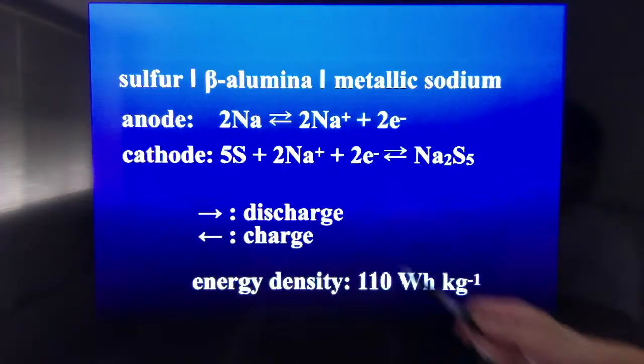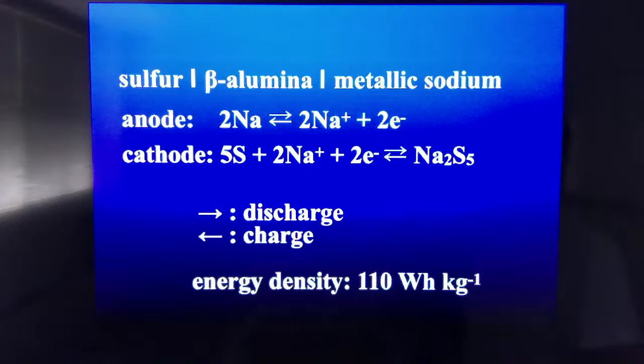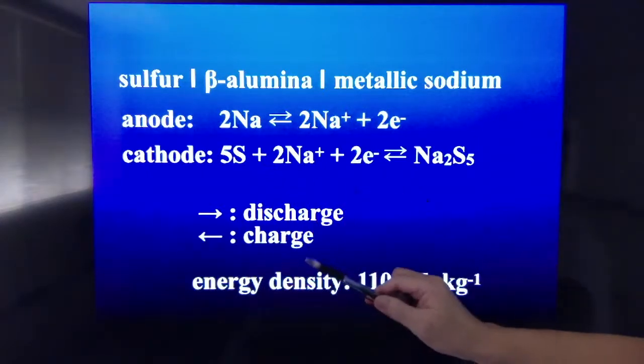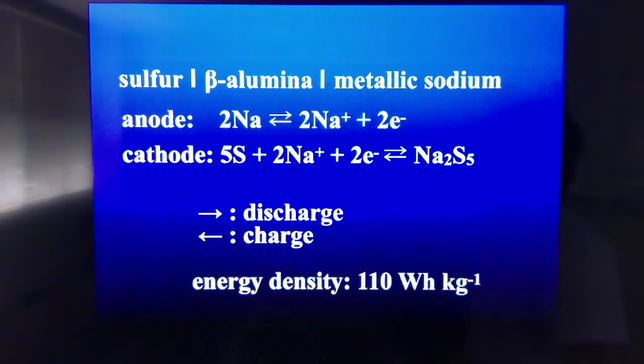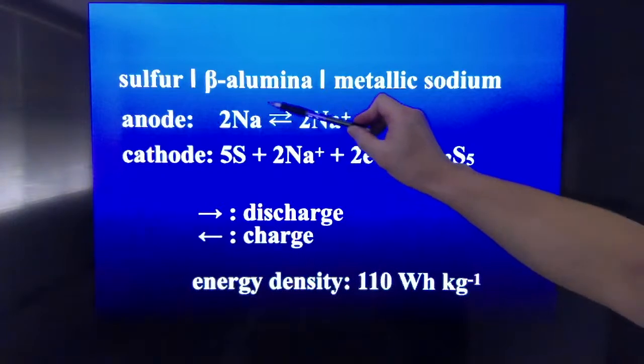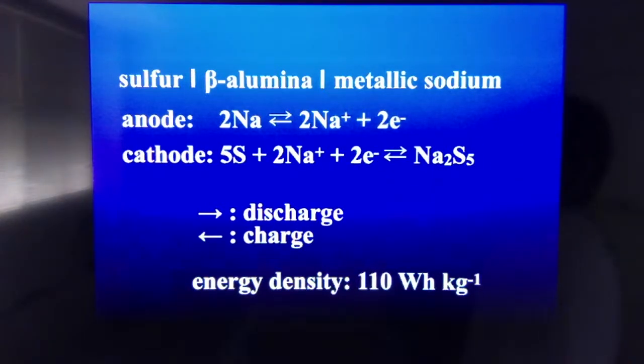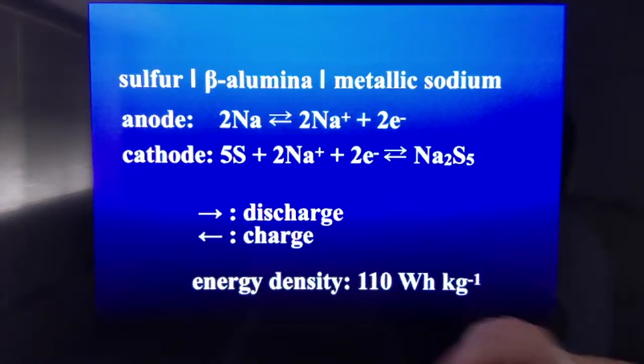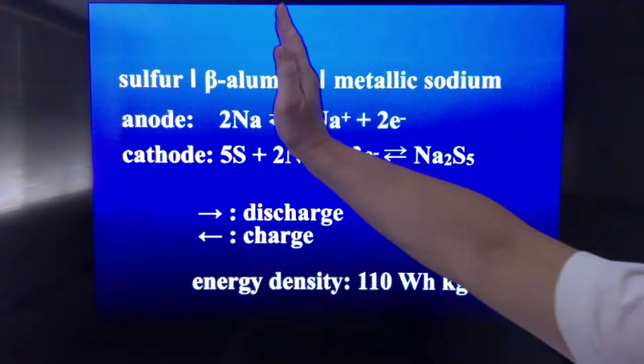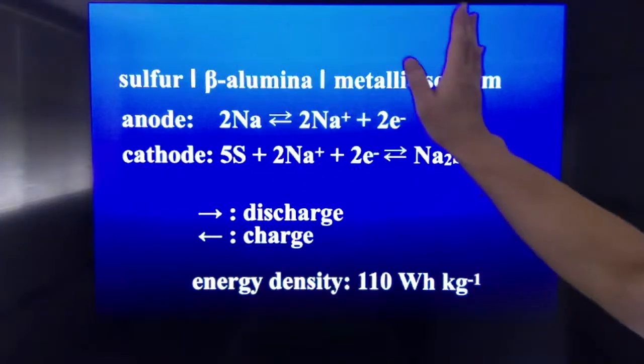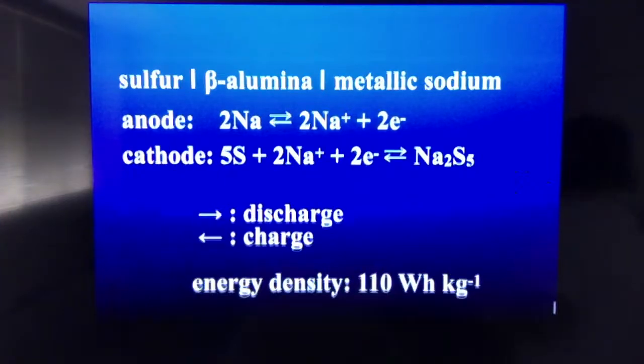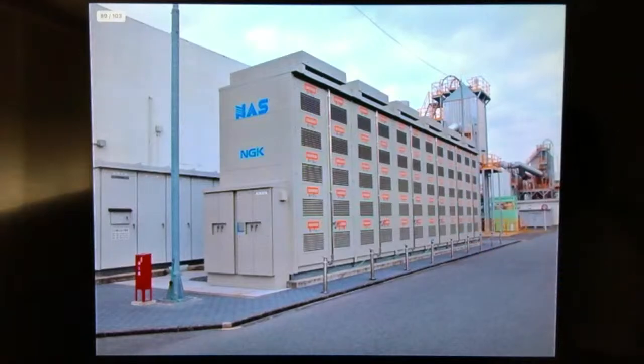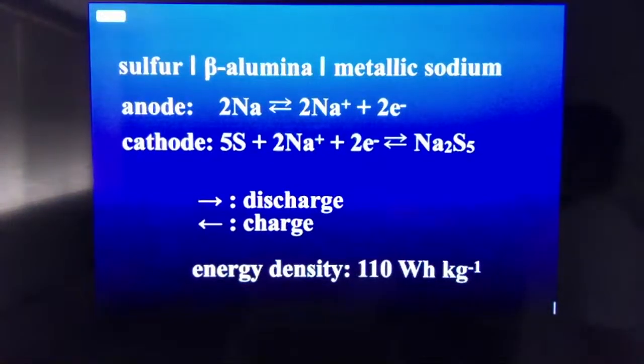NAS: N is sodium, Na, and S is from sulfur, S. So the anode is sodium and the cathode is sulfur. The electrolyte, beta alumina, starts the ion conduction at around 350 degrees centigrade. So at room temperature it is completely shut down. No conduction between cathode and anode, so no short. That means these are quite safe and very good for big storage in factories. Maybe not for cars.